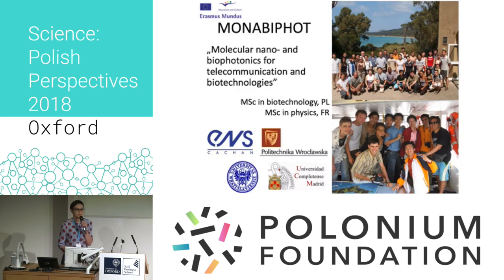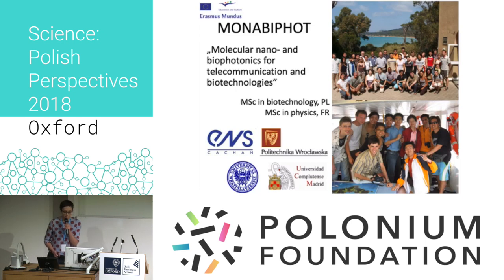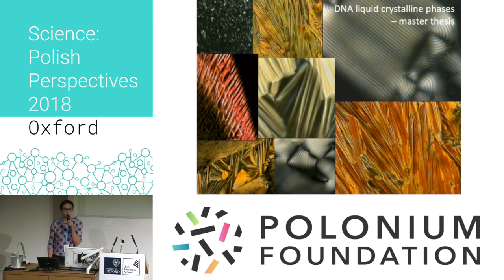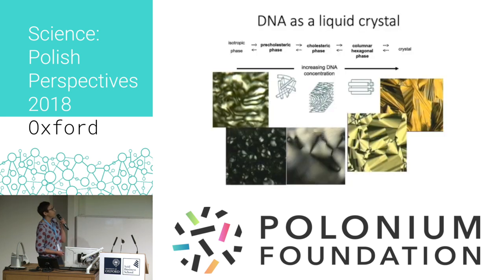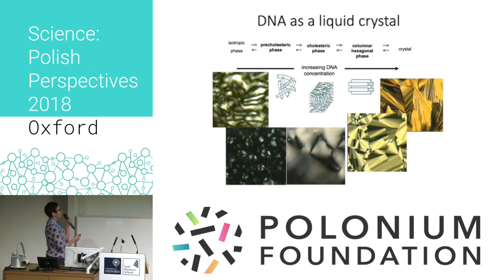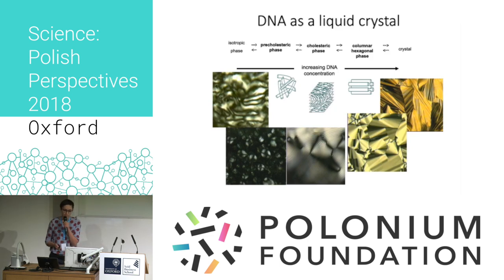There I decided this is what I want to do in my future. The program is in three different countries — France, Poland, and Spain — and it teaches you how to work on the border between physics, chemistry, and biology. With my master's thesis I investigated DNA liquid crystal phases. DNA is a lyotropic liquid crystal, and I treated DNA not as a functional biological molecule but as a biopolymer. I investigated how increasing concentration of DNA induces self-organization of strands from the isotropic phase to pre-cholesteric phase, cholesteric, columnar hexagonal, and up to the crystal phase.